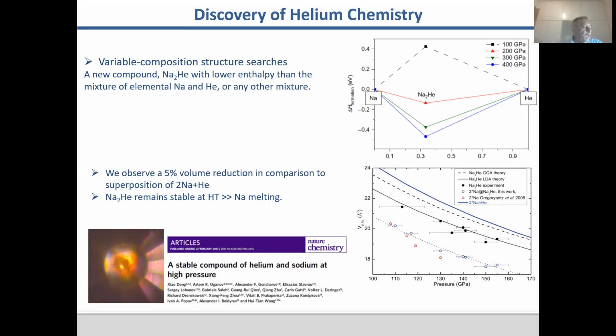So again, we see in the experiment this compound at about the predicted thermodynamic conditions, but we also found some very interesting results from the experiments. And here I show the equation of state. First of all, there was a 5% reduction in the volume of this compound in comparison to the elements, if you do the superposition, which strongly suggests a stable compound. But also during the laser heating, we saw that this compound was stable even under high temperature conditions, at conditions where sodium usually melts at this pressure. So this indicated that the bonding there is completely different than in sodium. This was also published in Nature Chemistry 2017, if I remember correctly.